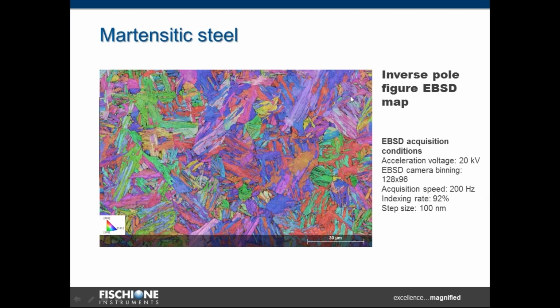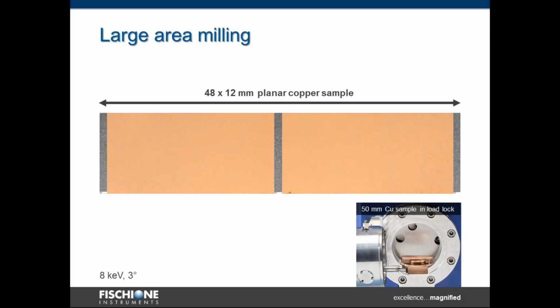As you can see here, we got very nice, high quality EBSD data from the whole big area, almost 30 millimeters wide. And if this is still not enough for you and you need to polish bigger samples or a bigger area, you can easily polish samples up to 50 millimeters diameter in area. Here we have an example of a copper bar, 48 millimeters by 12 millimeters.